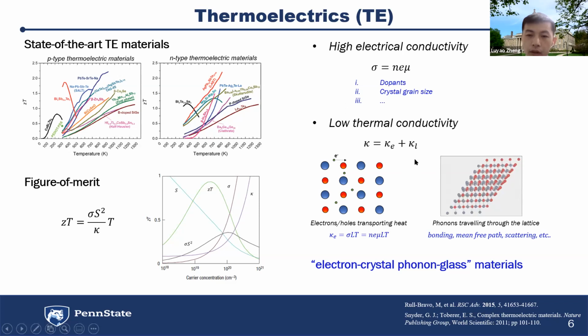If we want to get a lower thermal conductivity, we probably do not want to touch the electronic part, because if we try to reduce the electronic part, it also sacrifices the electrical conductivity. That means we can reduce the ZT value overall. So researchers mostly work on trying to get a low lattice thermal conductivity of the material. There are a lot of approaches, but people are always looking for new materials because the lattice is kind of an intrinsic quality parameter for the materials.